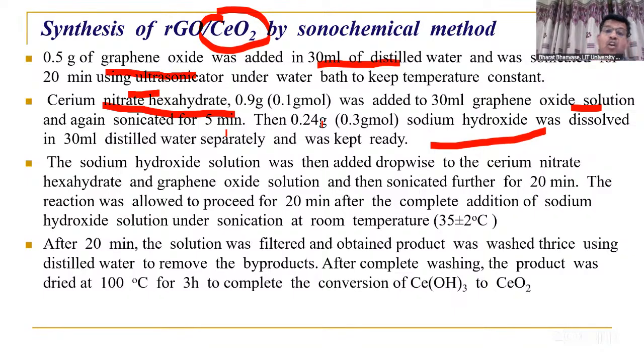Then 0.24 grams of sodium hydroxide was dissolved in another beaker and kept ready. The sodium hydroxide solution was added dropwise into the solution of cerium nitrate and graphene oxide, then sonicated for 20 minutes. That leads to the formation of rGO/CeO2 composite.